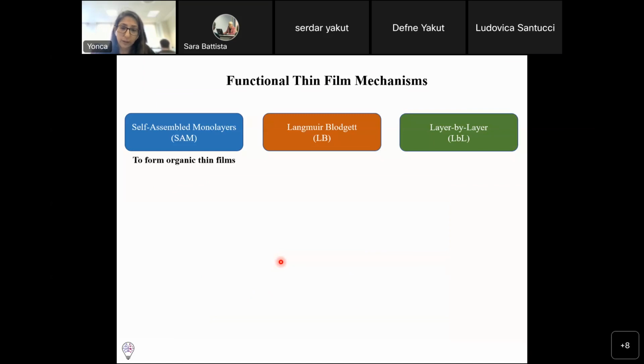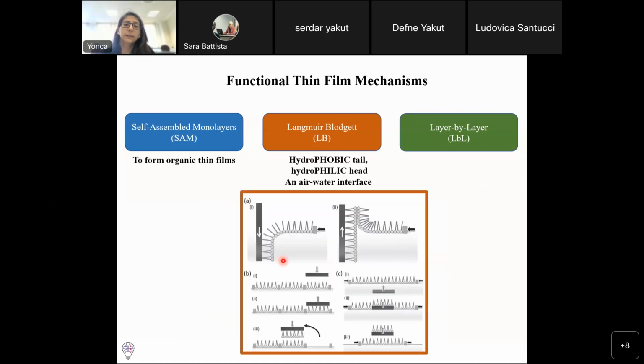In addition to that, in the 1900s, there is another thin film deposition technique that is named after two researchers, Irving Langmuir and Catherine Blodgett. Actually, this technique requires a specific condition. You need to have an amphiphilic molecule, which means that you should have a hydrophobic tail, which is usually a hydrocarbon chain, and a hydrophilic head, which is a polar functional group with a hydrogen bond. And in order to form a monolayer, you need an air-water interface.